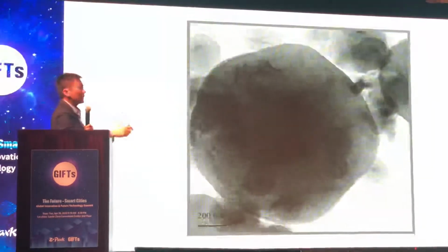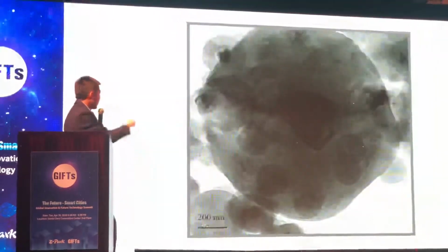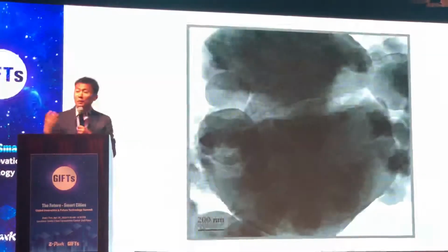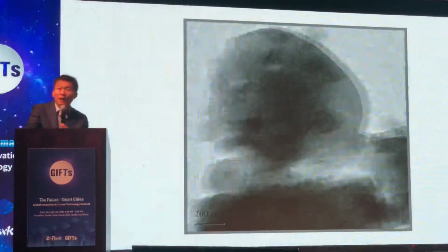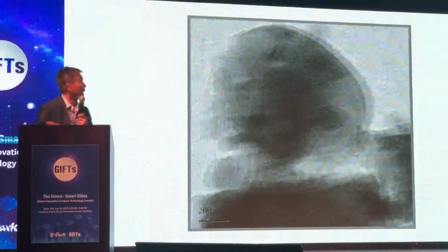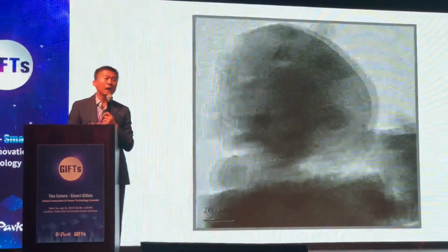Now, once the silicon particles start to take in a lot of lithium, they will start to break. You see, that causes the battery failure. Using research like this, we can identify how small the silicon really needs to be in order to avoid the breaking problem. The conclusion of our study has been guiding the whole industry moving forward.